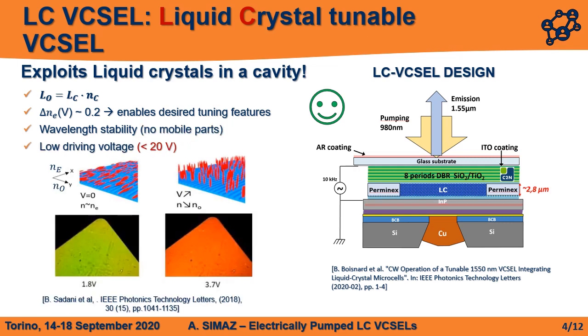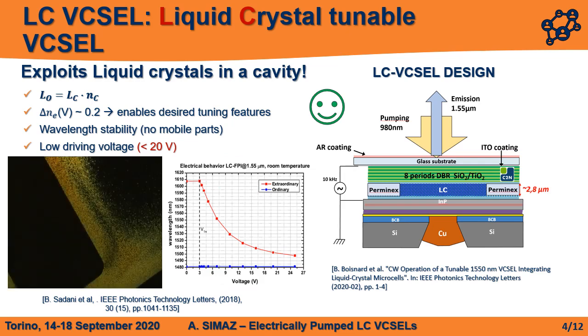The last benefit comes from the low driving voltage requirements, lower than 20 volts. The liquid crystal molecules are arranged along the grating grooves. At 0 volts, the mode sees the maximum value of the extraordinary refractive index, which is 1.72. By applying a voltage on the cell, the molecules start to tilt themselves and the refractive index starts to decrease until it reaches the value of the ordinary refractive index — in simple words, the material becomes isotropic. On the bottom, you can see two figures representing the different colors of the filter related to the refractive index variation of the liquid crystal. On the left is a nice animation of the liquid crystal molecules changing their orientation, and therefore the color, as the result of an applied voltage.